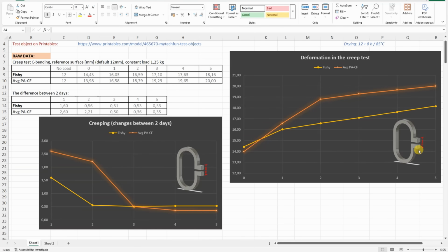On this graph you can see the distance between two reference surfaces, and we can see smaller deformation on the fishy filament compared to the average PACF, but as you can see this is under angle, and the difference between 2 days is the creeping. That's presented on the second graph, and we can see even on a day 5 from day 2 it has constant creeping of approximately half millimeters in this case, and this is typical for nylons. Sometimes the annealing may reduce this a little bit.